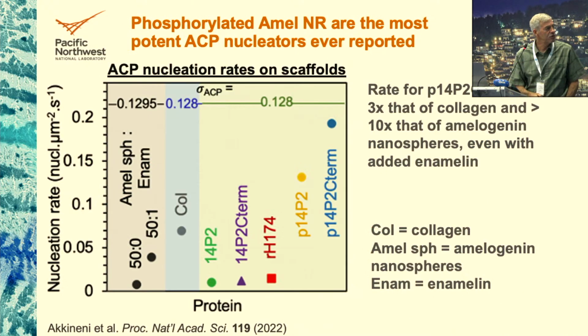So what do we find? Well, first of all, if we just look at the absolute rates and pick a place in supersaturation space where we've done experiments on other proteins, we find out that the phosphorylated amelogenin nanoribbons are the most potent amorphous calcium phosphate nucleators ever reported. So this is another form of amelogenin, nanospheres, which for more than a decade were thought to be the important motif in enamel and nucleation of hydroxyapatite to form enamel.